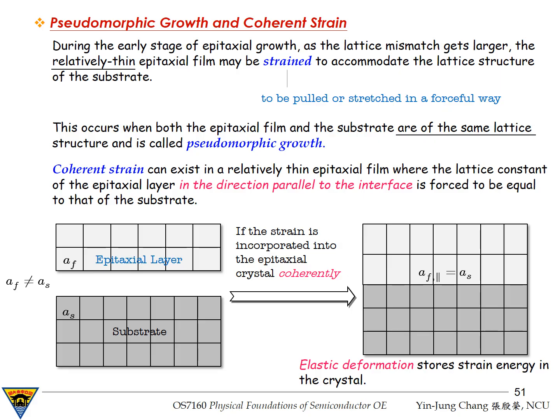For example, strained layers are widely used to modify band structures, enhance carrier mobility, and improve optical properties in modern semiconductor devices. So the key idea of this slide is that a thin epitaxial film can elastically deform to match the substrate lattice, resulting in the so-called pseudomorphic growth with coherent strain.